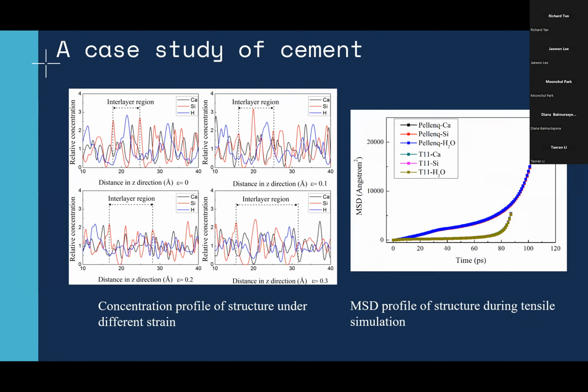So by performing the concentration analysis and the MSD analysis, we found that the binding interaction differences are basically caused by the situation that the electrostatic and bonded interactions between adjacent layers and the interlayer calcium are replaced by the water molecules. Also, the water molecules distributed in the region of the interlayer have an impact on structural deformation in the Z direction during the process of tension.